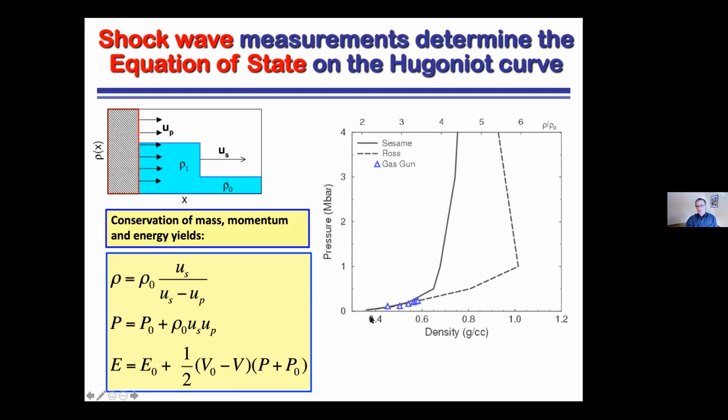So typically, you compress the material, pressure and density increase, and then it keeps going up, temperature's rising, it's not plotted here. And then typically you end up with a state that's close to fourfold the initial density you start. And when something like sixfold comes up, like it was predicted for hydrogen many years ago, then everybody scratches their head. That typically means that something in the material got excited, like electrons. So you will see lots of those curves.